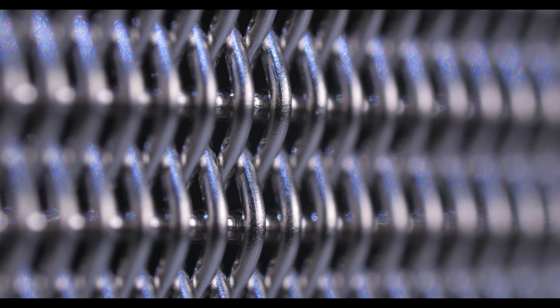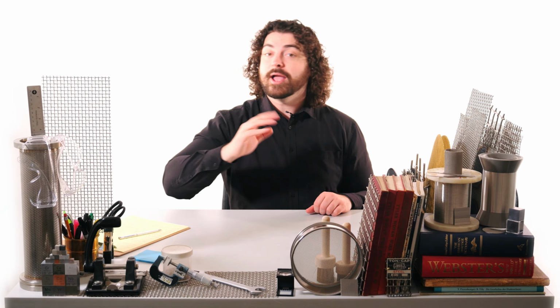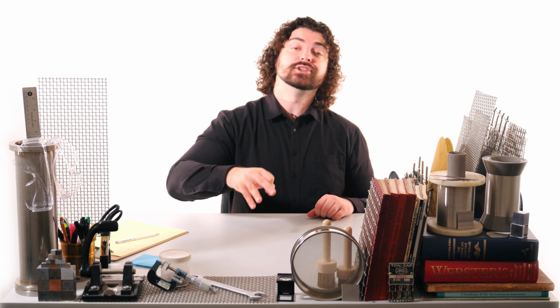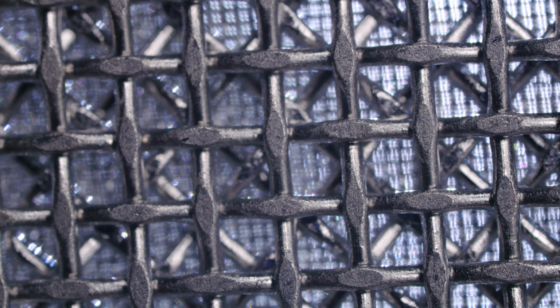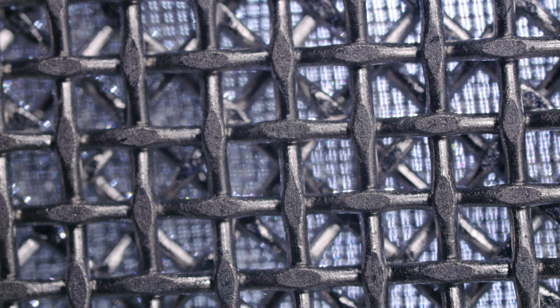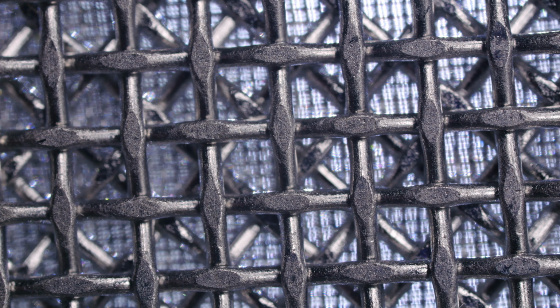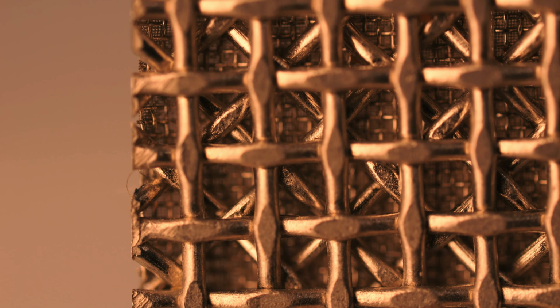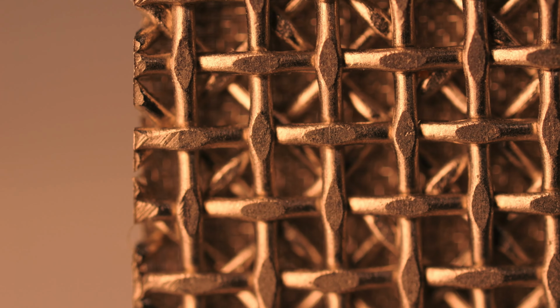The mean pore size and its distribution determine the filter's cut point, which is the smallest particle it can reliably capture. Narrowing the distribution improves fine particulate capture, but raises pressure drop and can slow cake formation. Conversely, high porosity and permeability reduce energy consumption and stabilize pressure drop. But if they're too high, emissions may spike before a cake forms. Engineers often use a graded laminate design, a fine surface layer for precision capture, supported by open layers for strength and flow. This approach balances emissions control with energy efficiency, a best practice confirmed by recent industry standards.